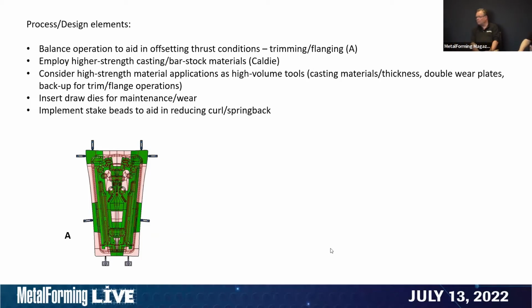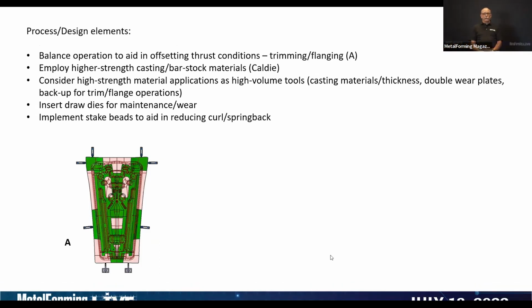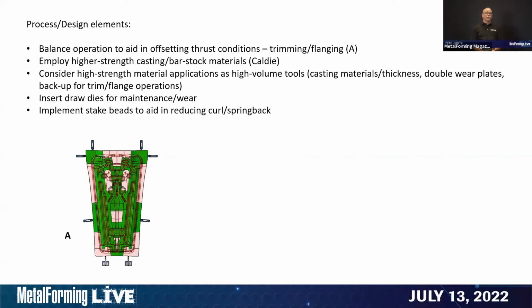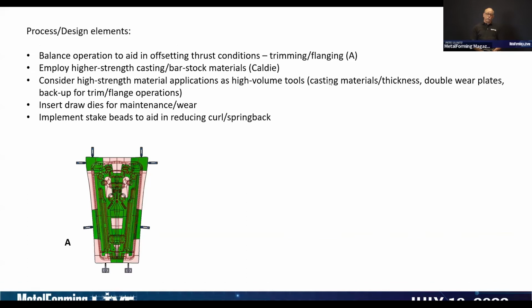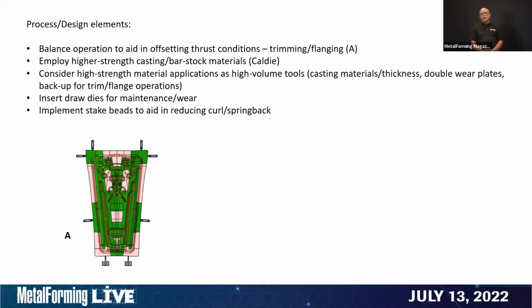I'd like to comment on that. So when we're looking at inserts on tooling, especially for these high strength applications, especially if you're running in progressive dies where you have a lot more vibration and heat that's being generated, we're looking for tools that are going to be wear resistant and have adequate toughness, and in most cases require a coating. So that's going to change our approach to our traditional view of tool steels. In these instances, you're going to be wanting to look at high-speed tool steels or powdered metallurgy PM tool steels, because these tool steels temper at a much higher temperature than A2 and D2 that we're typically used to working with. And this is what's going to fall in line with the PVD coatings, because these PVD coatings are applied at around 900, 950 degrees Fahrenheit, which is below the tempering temperature.